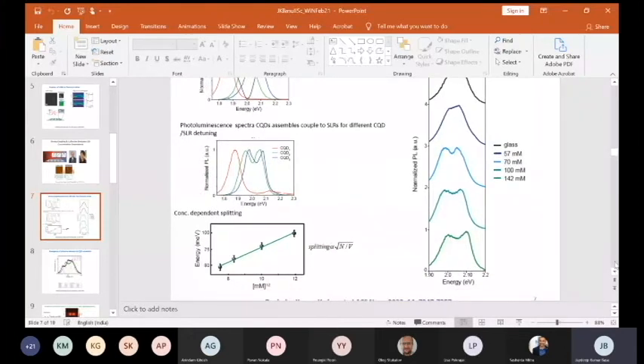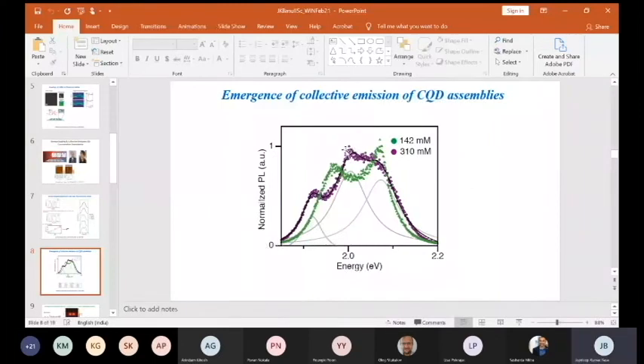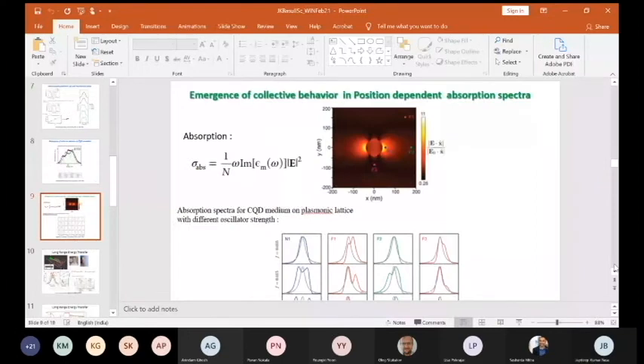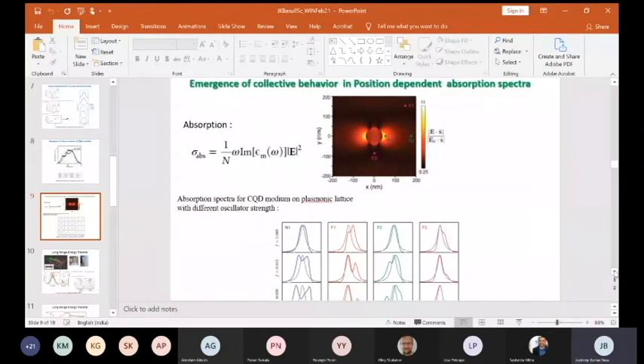But in the first part of the work, what we observed is that if you go on increasing the concentration, then at an even higher concentration, you start seeing the emergence of an additional mode. So there is even a third mode which appears, and there have been some recent reports in the literature with a different system using a transition metal dichalcogenide system. There are some reports of the emergence of this sort of additional mode, apart from the well-known upper and lower polaritonic features that one sees. So it turns out that when we ran some simulations, this was done with the help of George Schatz and his student and postdoc Charles and Mark.